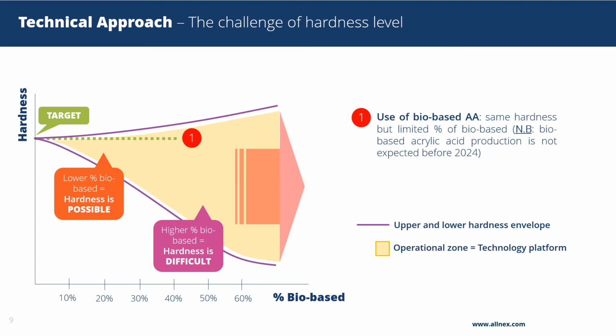The difficulty was then to assemble a bio-based polyurethane composition with biosourced molecules that preserves a high performance level, meaning a high cross-linking density. The higher the level of bio-based content, the more likely it is to reduce the cured coating hardness, defining an operational zone with a lower hardness envelope that is significantly depressed.